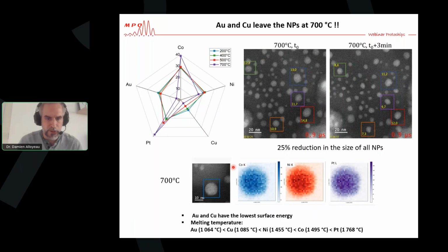And when you do the chemical mappings of the nanoparticles, you only have cobalt, nickel, and platinum left in the nanostructures. So it means that we have a segregation of gold and copper, and those two metals evaporate.